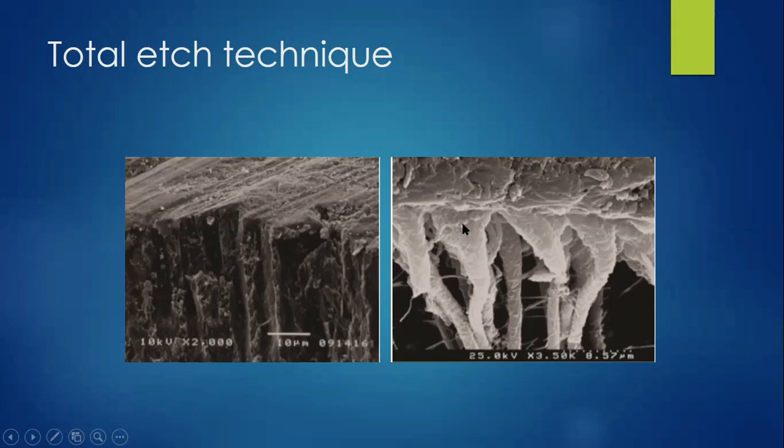It is very important to achieve diffusion of monomer to the level to which demineralization has occurred completely, but there are many factors for which we are not able to achieve that. It may be due to the superficial amorphous phase at the demineralized dentin surface. There is a parallel arrangement of the collagen fibrils in relation to the surface, and a presence of highly hydrated proteoglycan forming hydrogel in spaces between the fibrils. They don't allow complete penetration of monomer to the level to which the dentin has been demineralized.